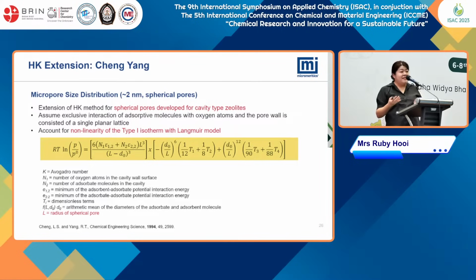There is also another extension from the HK model, Cheng-Yang, which looks into micropores less than 2 nanometers for spherical pores. Since pores might have different shapes, we use different models to address them. This assumption accounts for the non-linearity of the type 1 isotherm with the Langmuir model, assuming exclusive interactions of the adsorptive molecules with oxygen atoms, and the pore walls consisting of a single planar lattice. All these models are very well established, yet each has some assumptions involved for micropores.